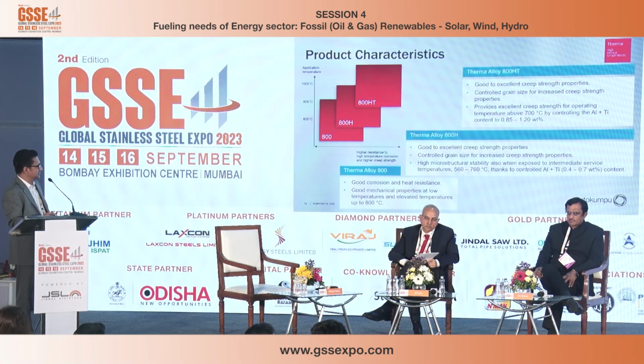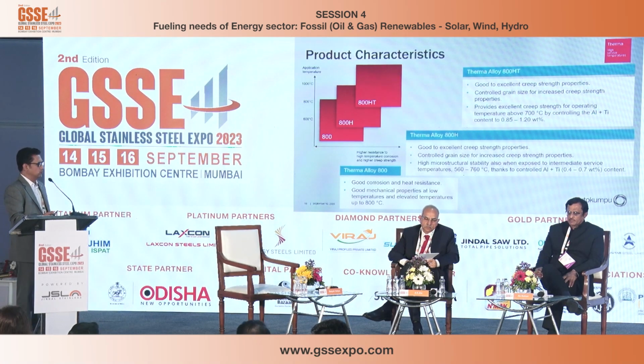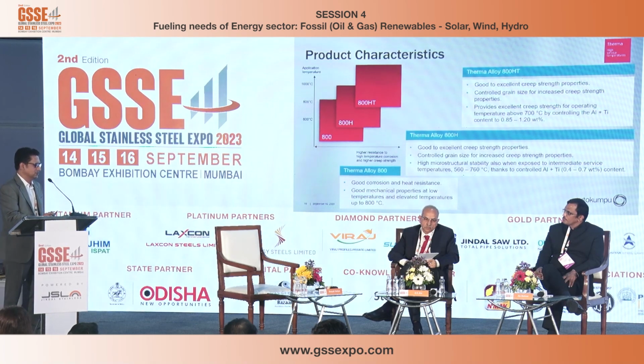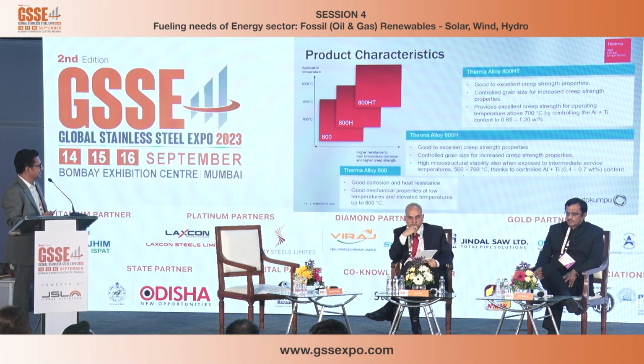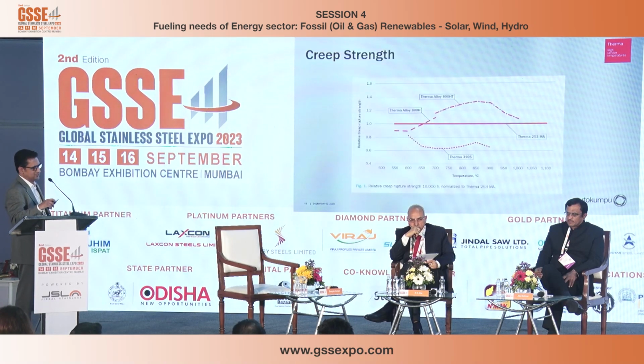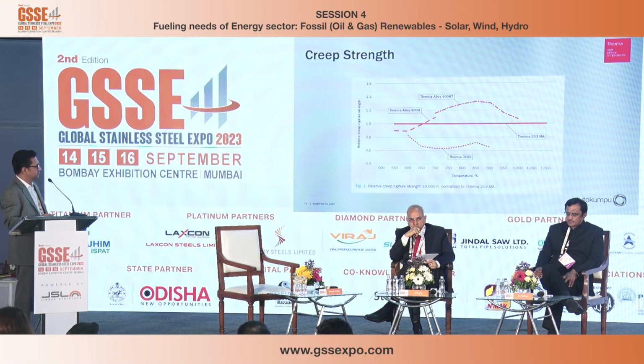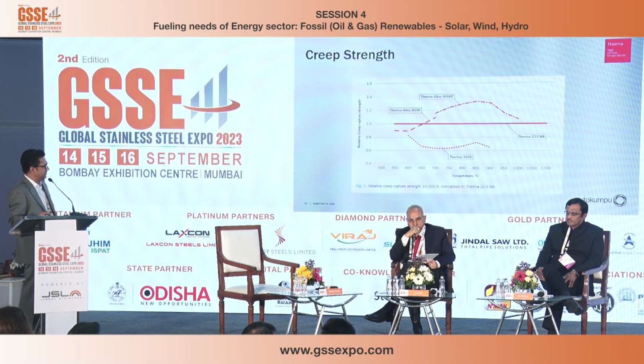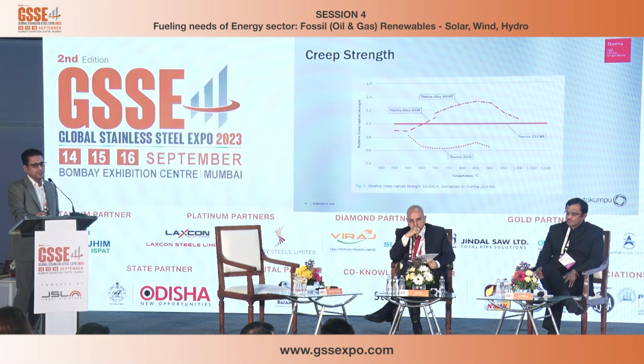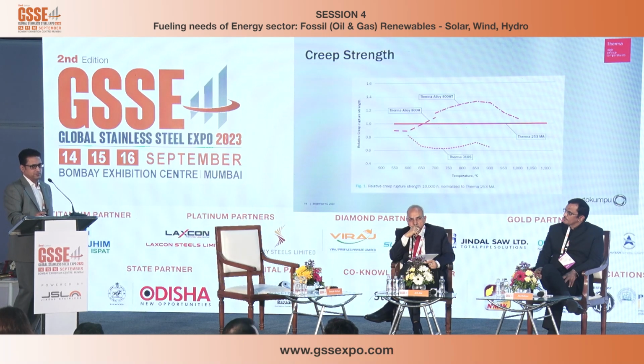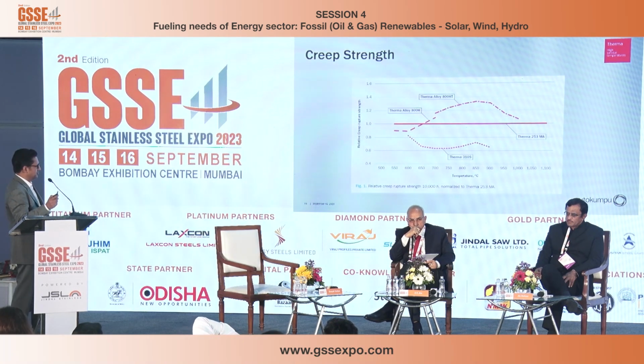Sir, you touched upon high temperature grades. You mentioned the supercritical boilers or high temperature grades. So this is something new, the addition of 800, 800H and 800HT. And these grades are capable of handling temperatures of more than 800 degrees centigrade. I'll not get much into these details, how it is done, but this figure is very important. The dark red line that you see is the 253 MA material, which is 253 with micro alloyed grade, which is presently being used up to 1050 degrees centigrade in the furnace or something.